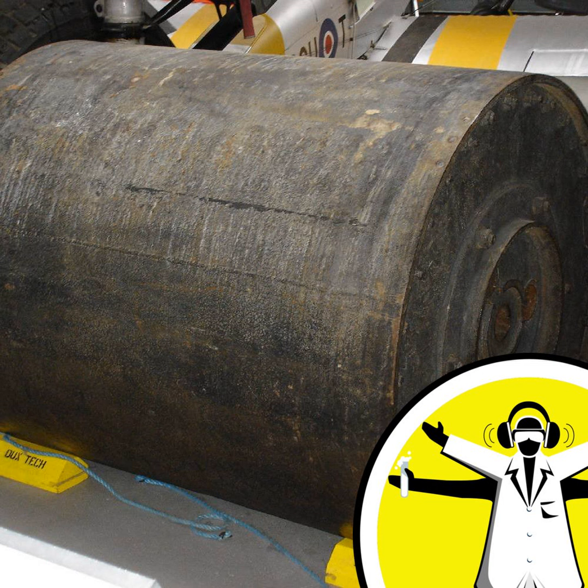Is this something that's controlled and monitored on industrial mines at the moment? In some mines it is. It's not necessarily controlled, although there's a move towards that. We'd like to see that implemented far more widely, and that this technique of monitoring the volume of froth overflowing is used as a control measure. If you look at a typical copper mine, we recover about 90% of the minerals that come into our process, and we lose about 10%. If we push that to 91%, that extra percent is worth, say, $20 million per annum. So there's a big incentive for us to get this right.